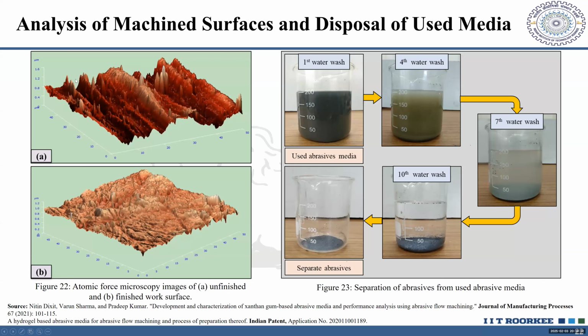You can see the surface finish. So this is the unfinished part. The surface finish is of the order of microns, but what you can see is that after you have done the finishing, all these peaks have flattened, and you are going to have a surface finish of the order of 0.8 to 1 microns. So that is the beauty of this particular media, that it can remove the material asperities even at a relatively faster pace.